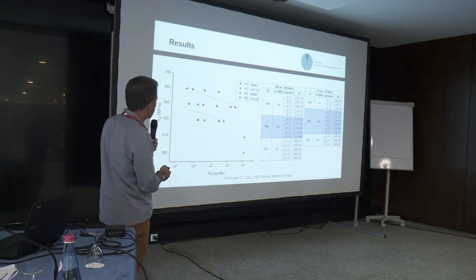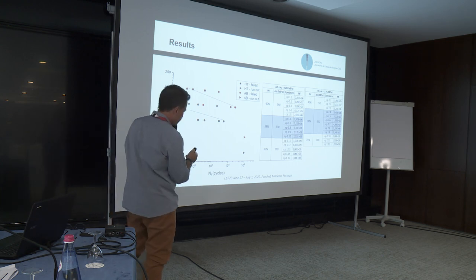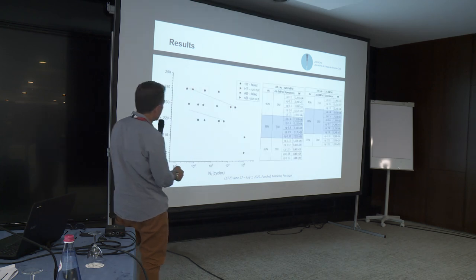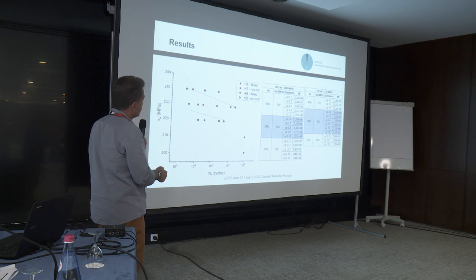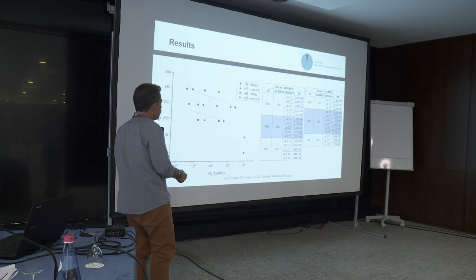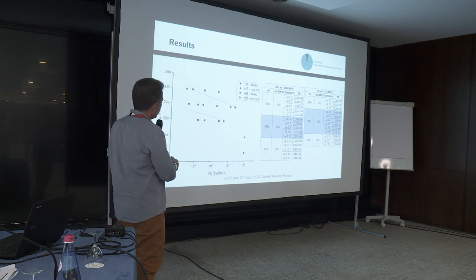Here you have the first results. The as-built material is in red and the heat treated in black. We can see that we have run-out specimens in both conditions after 10^9 cycles, but not a very large difference between the fatigue behavior of both, with something better for the as-built than for the heat treated.